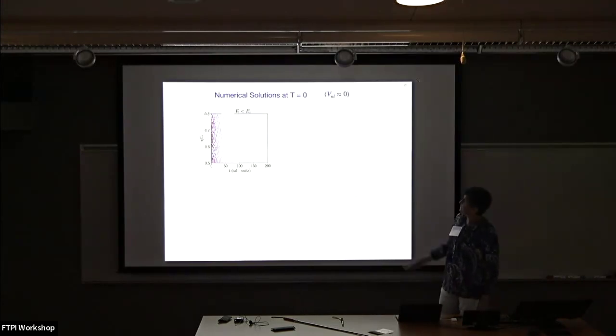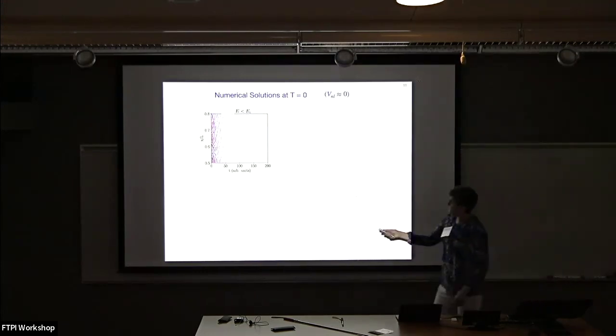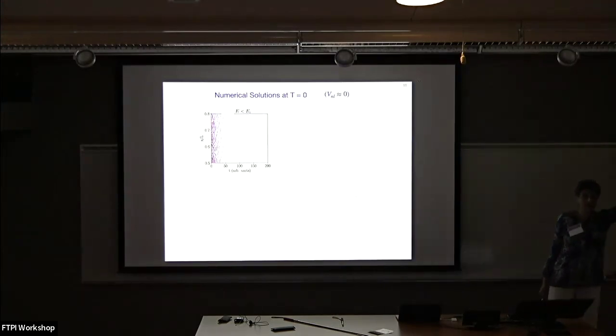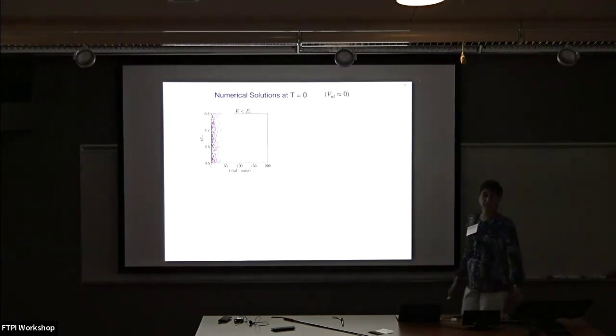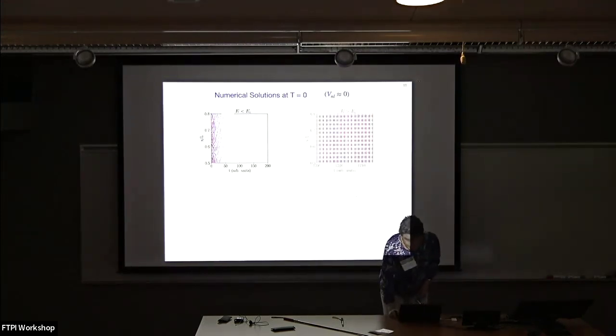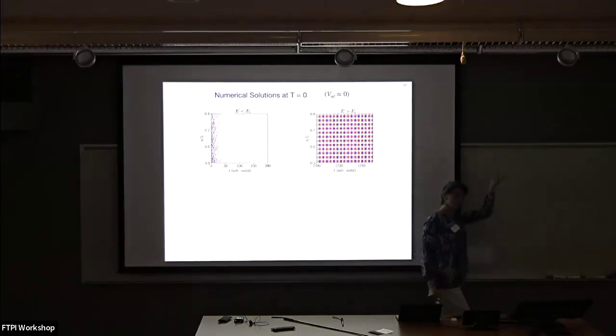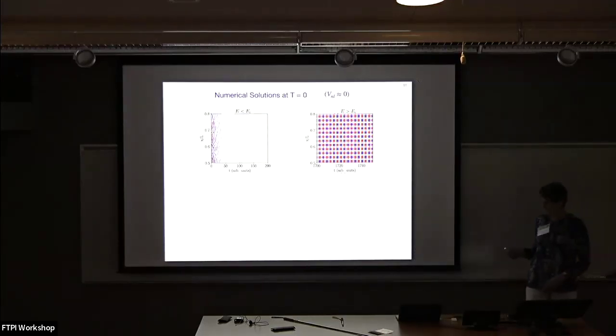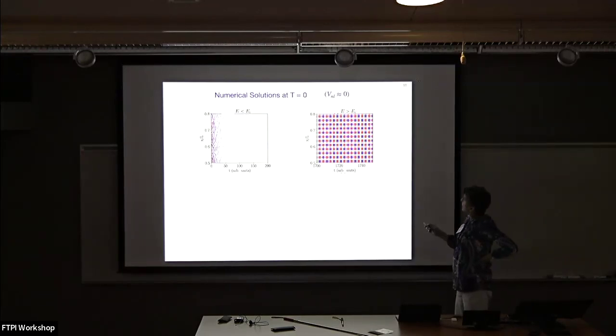So at low fields, E less than EC, what do we see? What we see is that the solution, and this is real space, a function of time, on the lattice, of course, decays exponentially. But now if we raise the electric field, what we get is this checkerboard pattern, and we see we have some ordering.